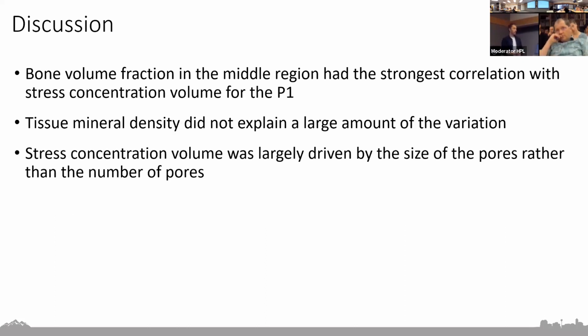And then with our regional analysis, we found bone volume fraction in the middle region had the strongest correlation with stress concentration volume, particularly for the proximal phalanx bone. And we found tissue mineral density did not explain a huge amount of the variation. So probably the degree of mineralization alone isn't enough to look at, but rather the microarchitecture might be something we should be focusing on instead. And with the microarchitecture, we found stress concentration volume was largely driven by the size of the pores rather than the number of the pores.